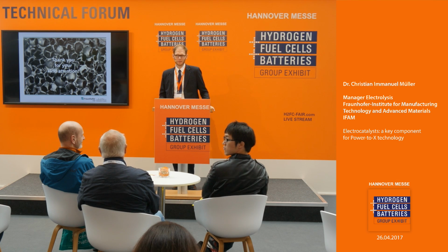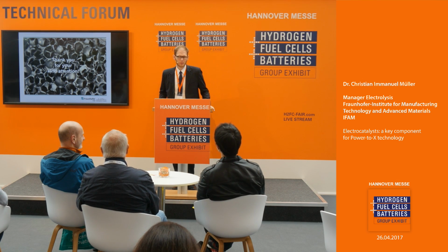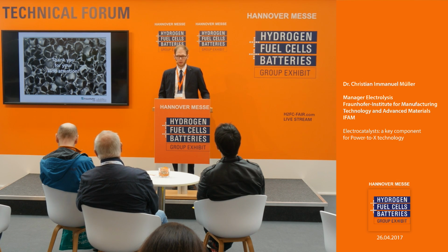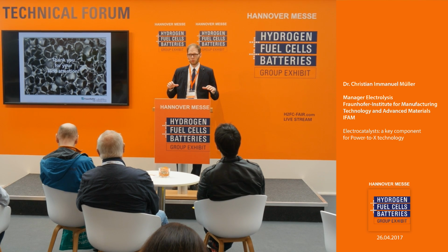Thank you for your interesting talk. These really highly structured catalysts, which are very efficient, you say, but how long do they last? What are your strategies to increase their stability over time? Yes, normally you have problems with brittle catalysts, for example, due to the hydrogen evolution reaction, you are right. So we have used this laser ablation process where you have still a solid material. So we have these cones, but these are very mechanically stable, even if you produce hydrogen, so the eruptive release of hydrogen bubbles from the electrode did not really affect your catalyst. It's very stable in this case.